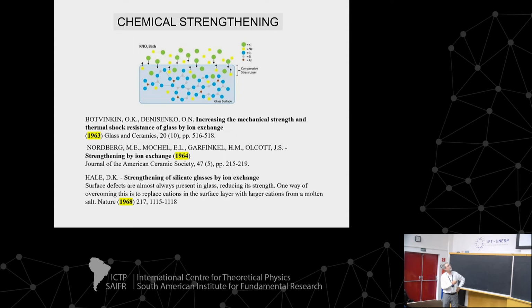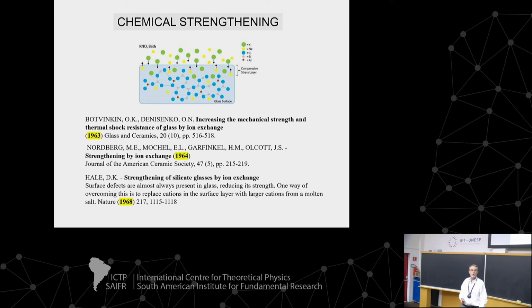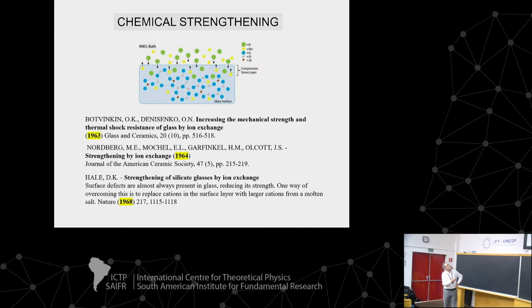This is a chemical strengthening. It's a very interesting method. You know, if you want to improve the strength of glasses, this is the worst property of glasses, low resistance to impact. You can do a chemical, thermochemical treatment. For instance, in a potassium nitrate bath at 400 degrees Celsius or so, the potassium ions exchange for sodium ions in the glass, and the surface becomes under compressive stresses. So they become much stronger than normal glasses. And funny thing that everybody cites the Nature paper, but the Nature paper was published in 1968, but the true inventors, these two guys invented this process years before the Nature guy wrote that article anyway, but you know this story. Anyway, let's take a look on the fracture of a chemically strengthened glass.